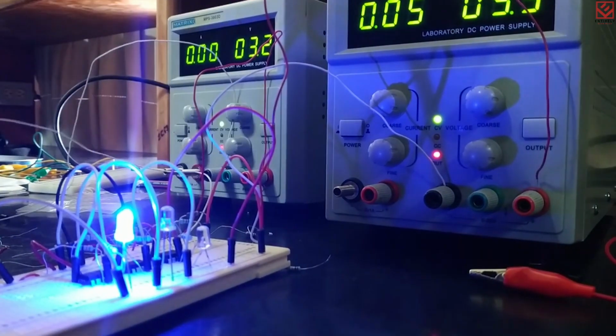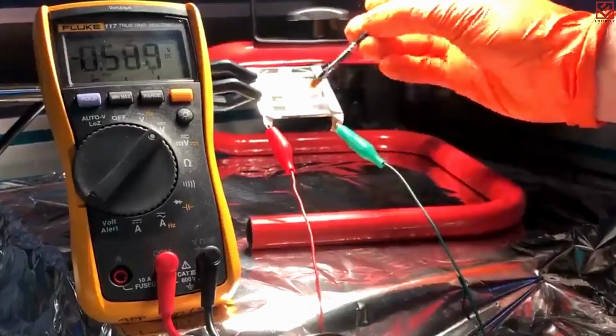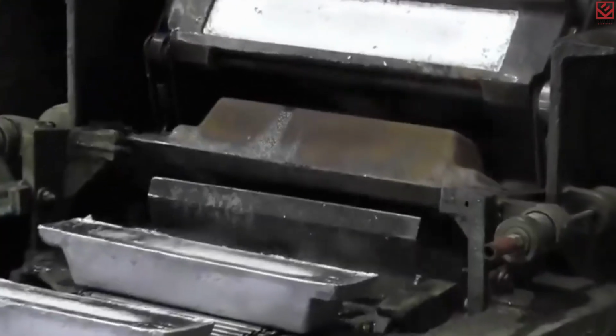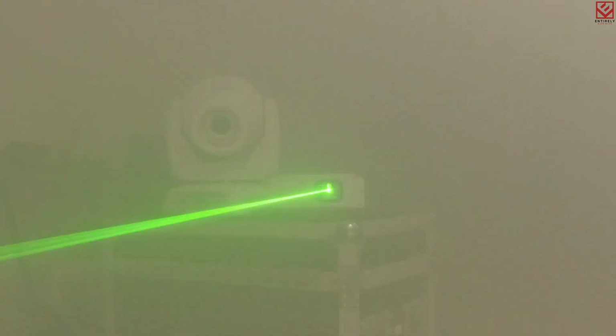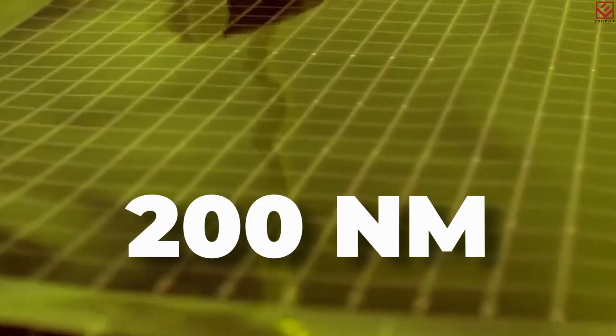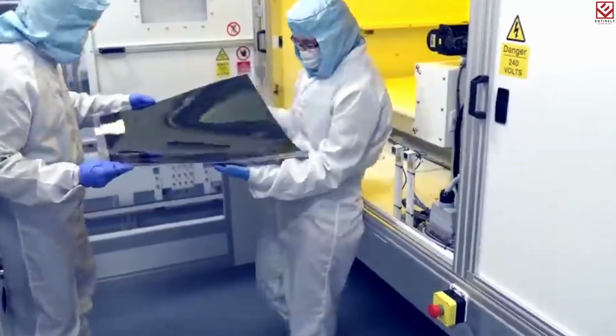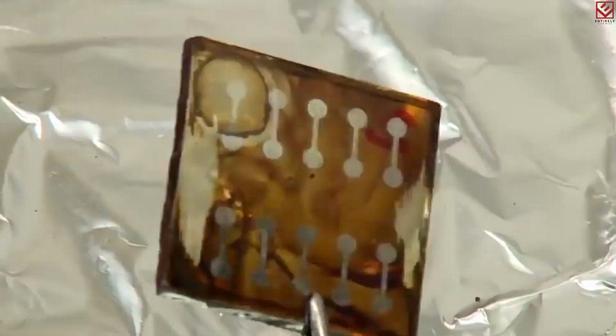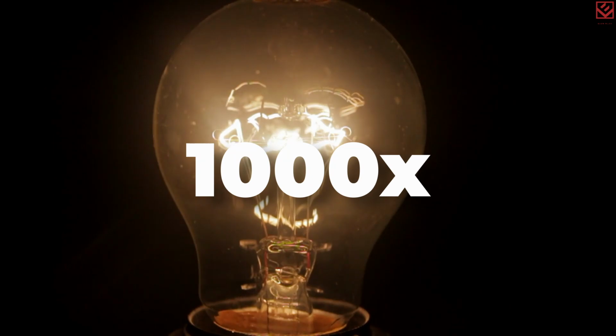By experimenting with different material combinations, the researchers discovered that combining extremely thin layers of different materials significantly increases the solar energy yield. This was accomplished by vaporizing the crystals and redepositing them on carrier substrates using a high-powered laser. Compared to pure barium titanate, this resulted in a material with 500 layers of about 200 nanometers thick. Even after reducing the proportion of the base element of the mixture by nearly 2/3, the new photoelectric material irradiated with laser light had a current flow that's 1,000 times stronger and more efficient.